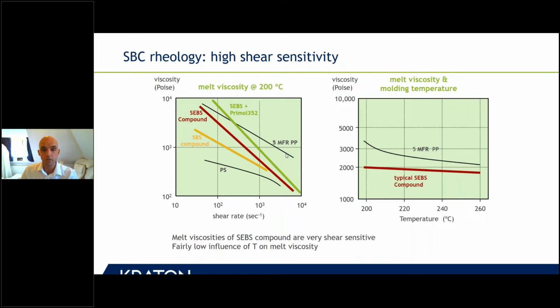We do actually give our polymers melt flow rates, but they can sometimes be misleading, because if you put on more shear, it actually flows a lot better. So sometimes you see some of our polymers which have a fairly low melt flow rate, and if you use them in an extrusion or an injection molding process and put on a shear of like 1,000 or even higher, you can process it, and it flows pretty well. If you look at the melt viscosity depending on molding temperature, it's a fairly flat curve. So it also gives some processing robustness if you compare it to, for instance, just a polypropylene.